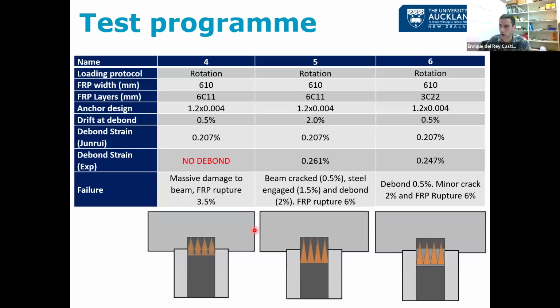So we decided to try different detailing mechanisms or options, and we were able to bring back the original response where the debond happens at around 0.2, 0.25. We have a minor crack and then debonds until 6% lateral drift. So this is working, and we know that we can make it work. Next step is to apply both rotation and tension.